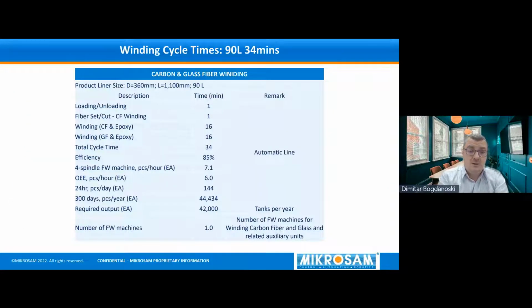The winding cycle to produce this one size of 90 liter CNG tank is 34 minutes. And here you can see how this is spread out through different functions. Just to mention, the diameter was around 360 millimeters and the length was 1.1 meters. For loading and unloading, we need around 1 minute. For automatic fiber cut and restart, also 1 minute, both for carbon and glass fiber. Then, since it's 50% carbon fiber and 50% glass fiber, we need around 16 minutes per each winding fiber. And this gives us a total cycle time of 34 minutes.